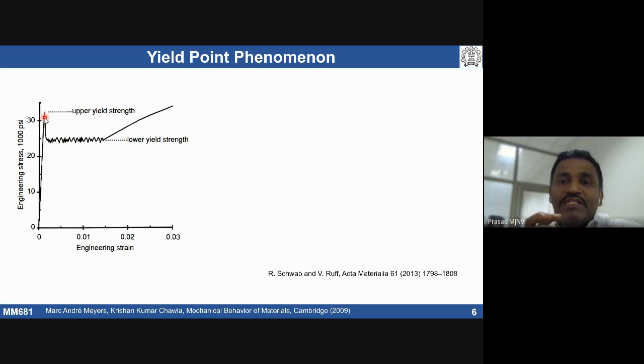Dislocations are going to interact with the solutes, because we have a favorable combination of strain rate and temperature, which facilitates interaction between the solutes and dislocations. During elastic deformation itself, a certain amount of this activity is going to take place - these interactions. So when the solutes are getting... assume I have a certain number, n number of dislocation density.